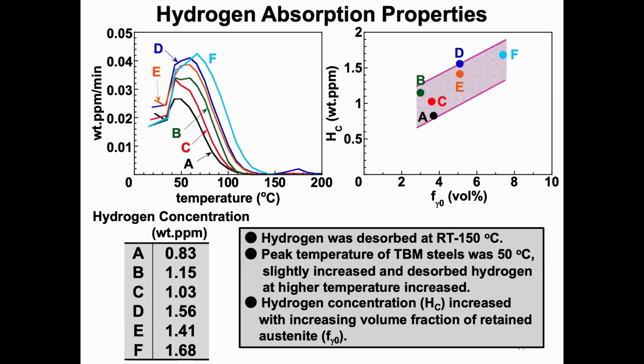These figures show the hydrogen desorption curves and the relationship between hydrogen concentration and volume fraction of retained austenite in the TBM steels. The hydrogen concentration calculated from the hydrogen desorption curve is also shown in the table. The hydrogen was desorbed at temperatures between room temperature and around 150 degrees Celsius, and the peak temperature was approximately 50 degrees Celsius.